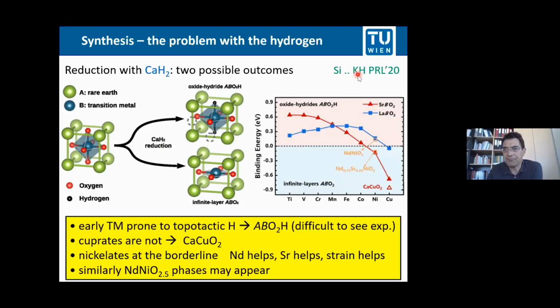And what we have done here last year is a calculation of the binding energy for the hydrogen. So we take this infinite layer structure and calculate the energy we gain to bind the hydrogen. And you see here positive binding energy means the hydride phase is energetically favored. And indeed, we find that for the early transition metals. For the cuprates, on the other hand, it is preferable to have the infinite layer structure. And the nickelates are just at the borderline where it's very balanced. So the undoped compound in blue here is the lanthanum nickel O2, but also the neodymium nickel O2. They prefer, energetically at least, to have hydrogen intercalated.